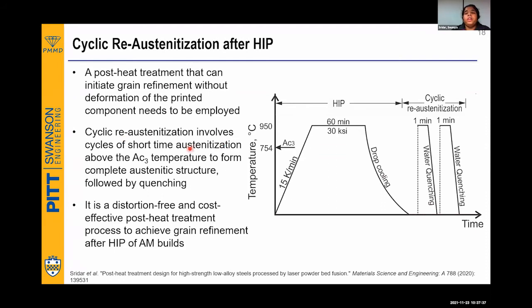What are we going to do? After this cooling has happened, we are going to re-austenize, that is, take it to 950 degrees C again in a furnace without any pressure, that is above the Ac3 temperature, for a very short time. You see, we have done just 1 minute, and then immediately water quench. Not normal water quench, but ice water quench. And again, one more cycle we are doing. So this is one cycle: heating, holding for 1 minute, cooling, heating, holding for 1 minute, cooling. This is cycle 1 and cycle 2.